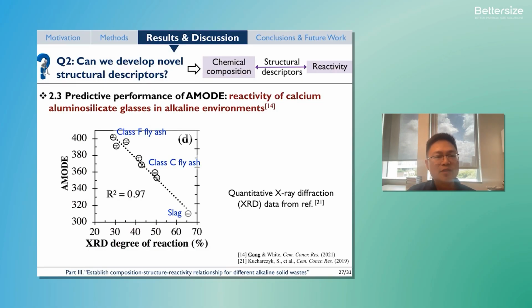Right? So this trend is consistent with expectation, because a sample with a lower Amode value means it takes less effort to dissolve the sample to allow it to participate in reaction, right? And therefore, the higher extent of reaction at a given time, right? So this kind of inverse correlation is consistent with our expectation.